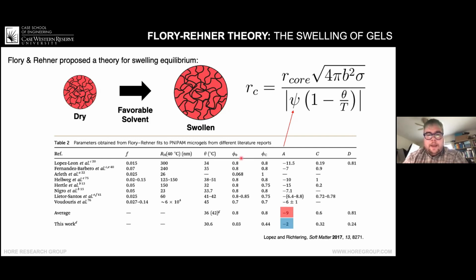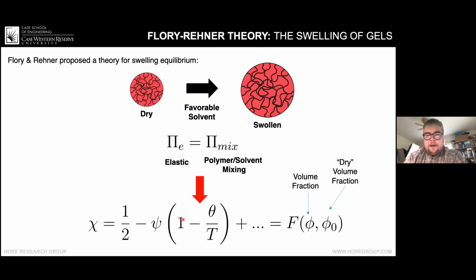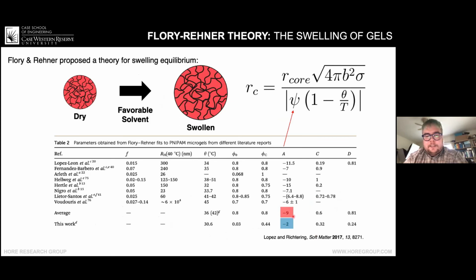But I do want to point out one major issue with using the Flory-Rehner model. When we combine all these terms together and express the Flory-Huggins parameter as a function of the volume fraction of the swollen gel and the dry volume fraction of the original network, getting this value is one of the big problems. That's the reason these authors claim there's such a discrepancy between the values they get for this parameter and the values given in the literature. For example, phi 0 is the volume fraction of dry polymer. In the literature, they calculate this to be 0.8. When they redid their analysis, they said that for the volume those particles take up, the polymer is actually only 3%. So maybe this is the bigger issue, at least in this application of the Flory-Rehner theory, than other ones.